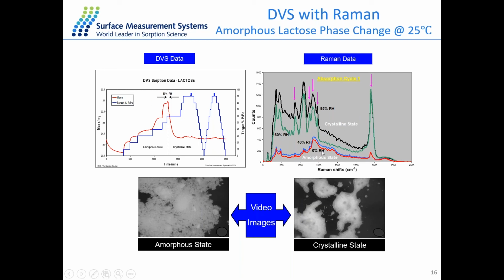And we took those Raman spectra at the end of each stage when it reached equilibrium. Here the Raman spectra at 0 and 40% RH show a very broad peak, indicating the amorphous state. And exactly above 60% RH, there are some new peaks showing up here. That indicates the crystalline state. So this Raman spectra confirms our observation in the DVS data that the sample goes through the amorphous to crystalline phase change at 60% RH. The whole setup here, with the DVS as well as the Raman and the video camera, gives us a full idea about these material changes at different humidity.